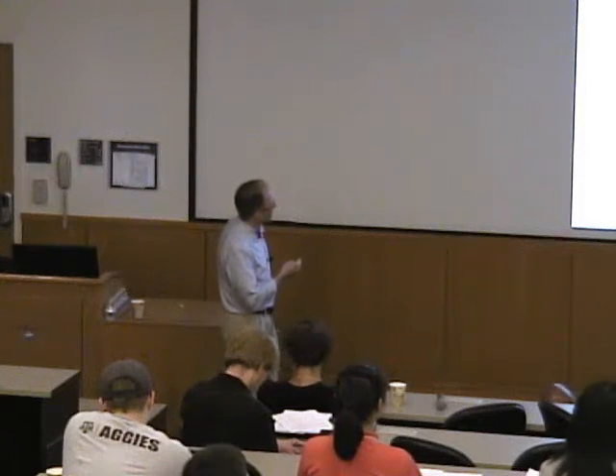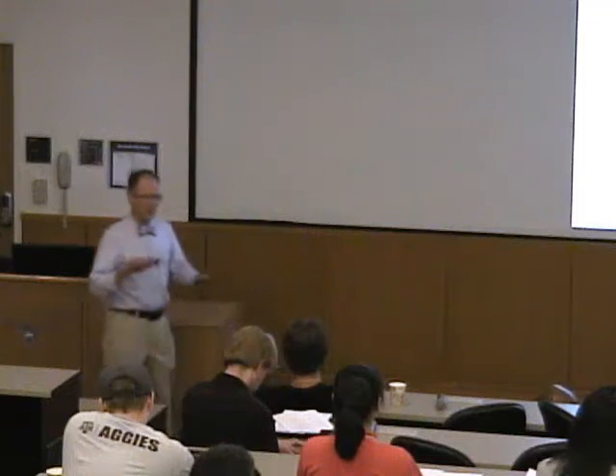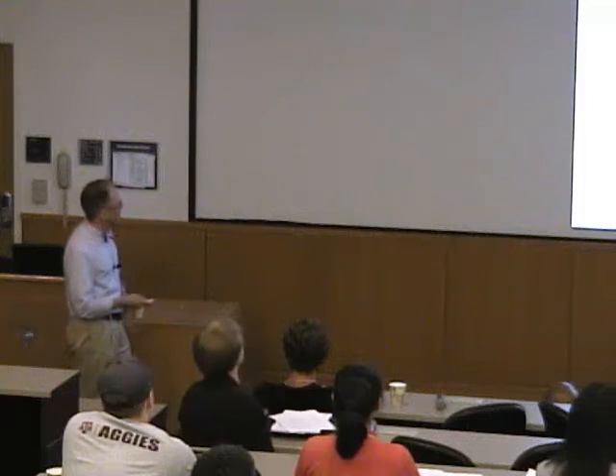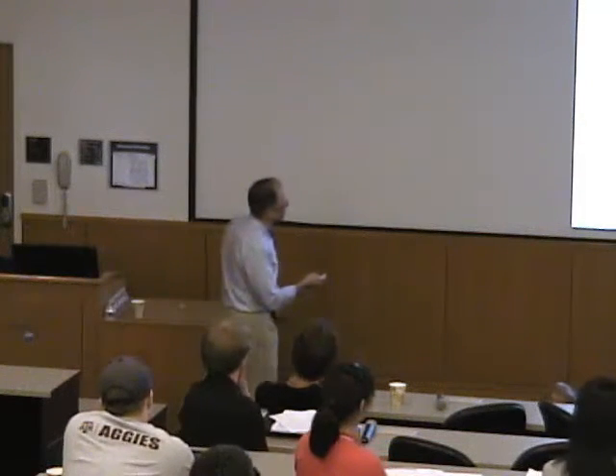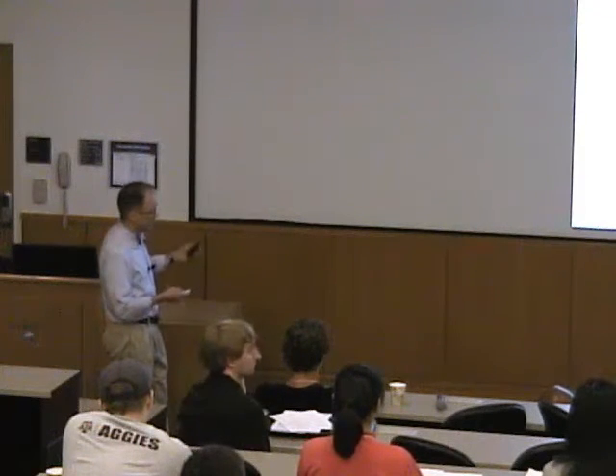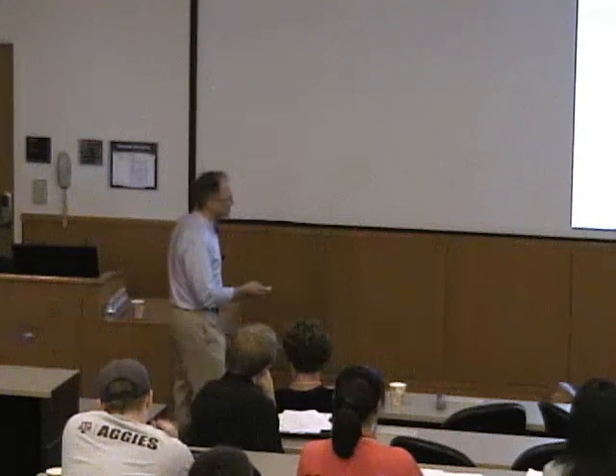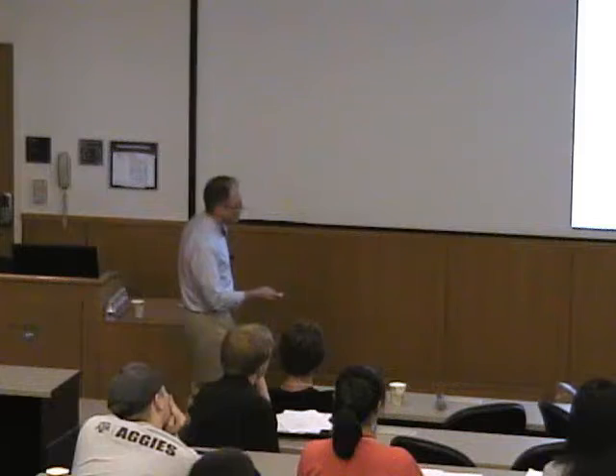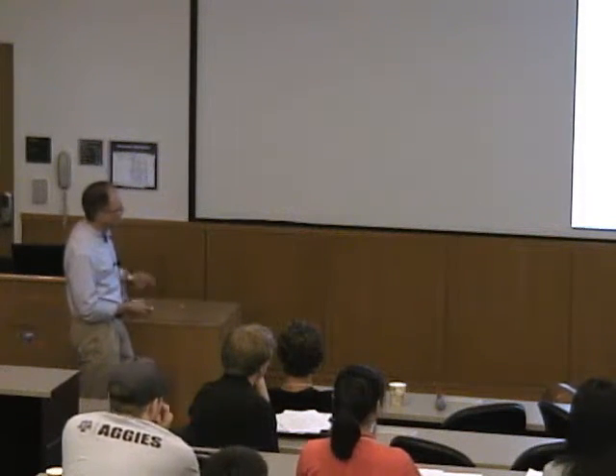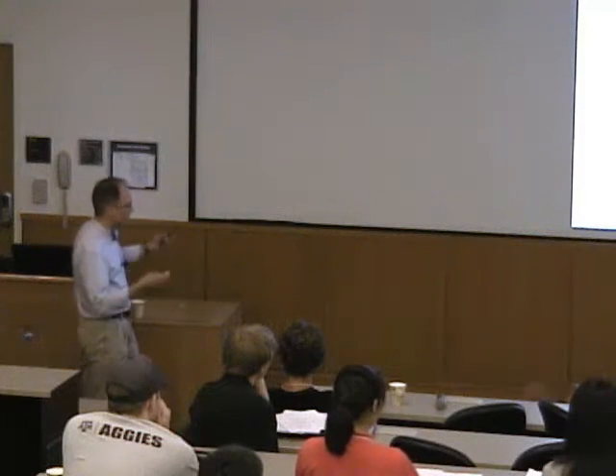And so with the standpoint of a bit of the electron transfer theory, the idea is that fundamentally, and I realize this is a bit out of order, it would be great to have this portion follow David Beratan's talk, so I'll just summarize in some way. But the notion being that we can think about what Marcus theory predicts in terms of an electron transfer rate, and that there's a dependence upon an electronic coupling term, there's going to be a dependence upon what the actual driving force is, and the reorganization energy associated with the redox reaction that would be at work. And that we're going to see that the coupling will go down, the rate of electron transfer will decrease as we increase that distance.